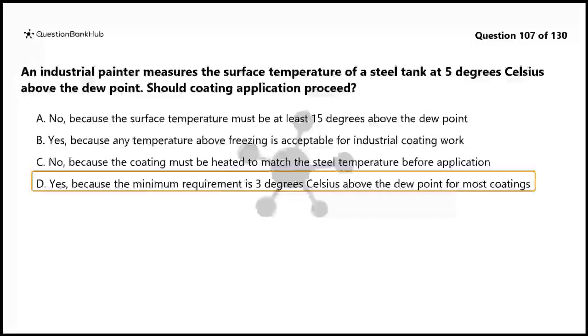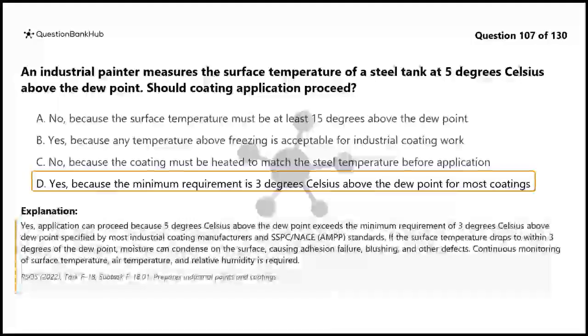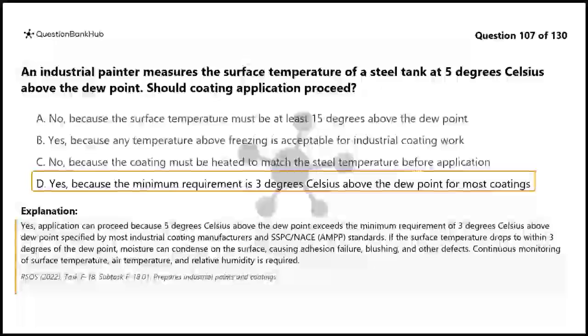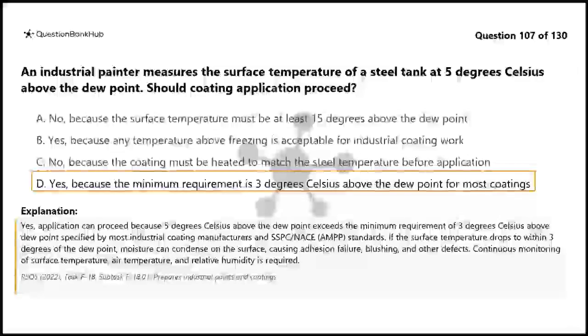The correct answer is D. Yes, application can proceed because 5 degrees Celsius above the dew point exceeds the minimum requirement of 3 degrees Celsius above dew point specified by most industrial coating manufacturers and SSPC/NACE, AMPP standards. If the surface temperature drops to within 3 degrees of the dew point, moisture can condense on the surface, causing adhesion failure, blushing, and other defects. Continuous monitoring of surface temperature, air temperature, and relative humidity is required.